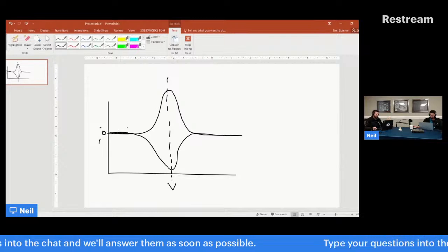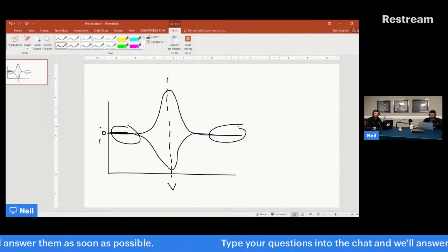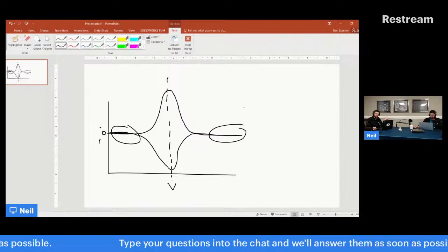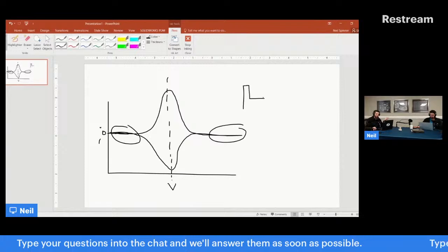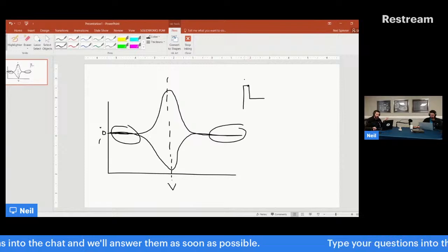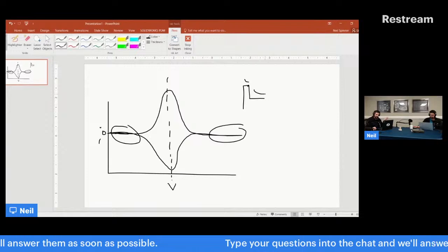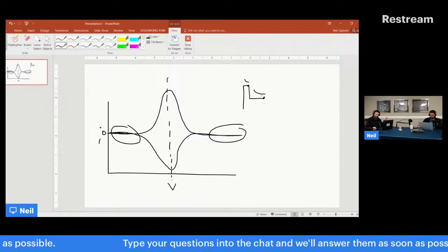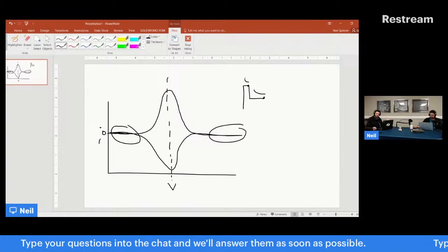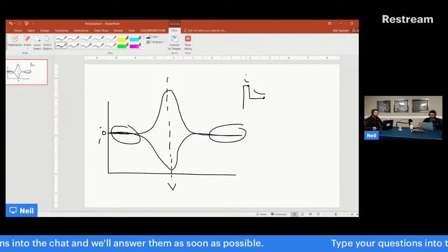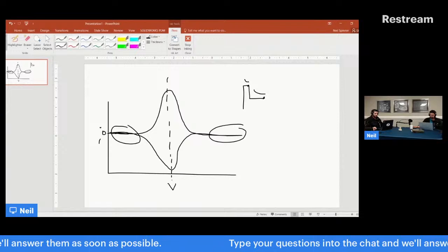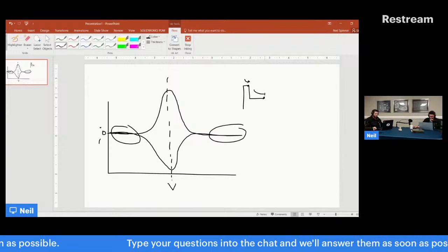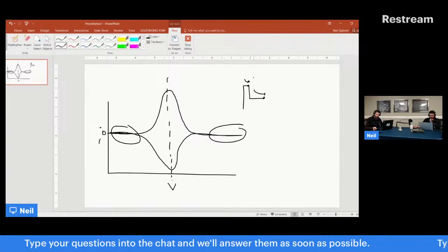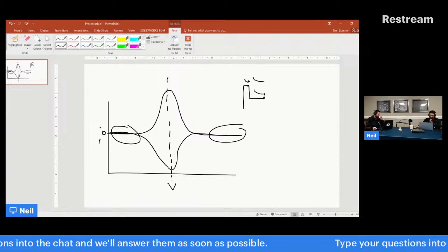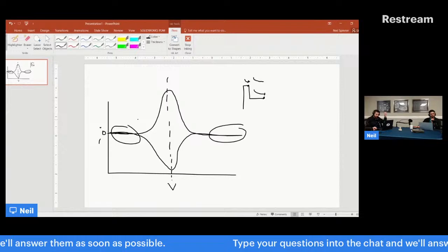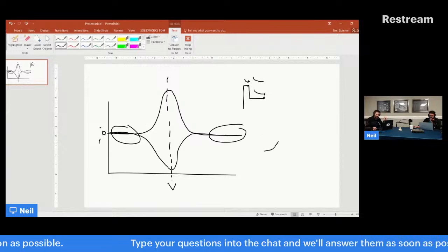Over here and over here, there's no Faradaic processes happening. So the effect of jumping up and then dropping back down is that you have some settling of the current here and some settling of the current here. Even though they're different lengths of time, there's no Faradaic process. It's a quick setup of the double layer. So this current minus this current is basically zero. I know I've drawn them in different locations; I should have drawn them here. Effectively, the difference of the current is going to be zero until I start having a Faradaic process.